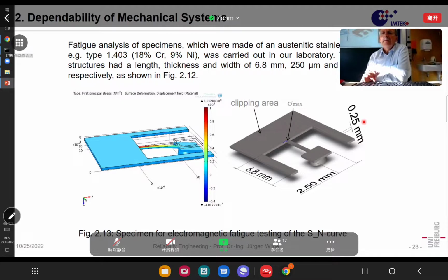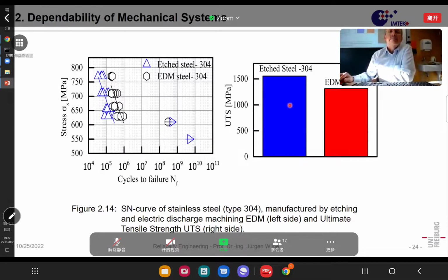And we did that test. And now he did several steels. When you produce small steel parts, that steel 304 is something like a stainless steel. And in that way, we wanted to investigate what the effect of the machining was. One was etched material, just in an acid with photolithography, and the second was electrical discharge machining. You have a wire, and that wire gives a spark against your part, and that spark takes out some cubic micrometers of material, and in that way you can machine it.